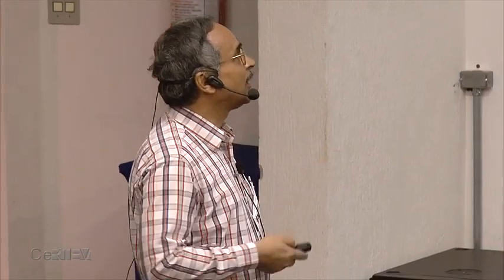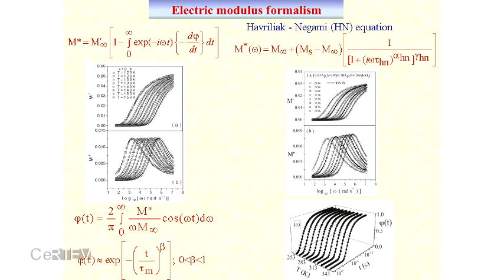We can see here the modulus representation. I have seen many authors prefer to represent data in this way. This is the real part, and this is the imaginary part. In the modulus representation, the electrode polarization effect is suppressed. So this formalism has some advantages, and it is very easy to analyze. The peak in every material occurs because of the nature of the imaginary part of the modulus by definition.